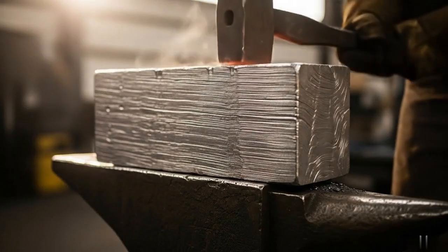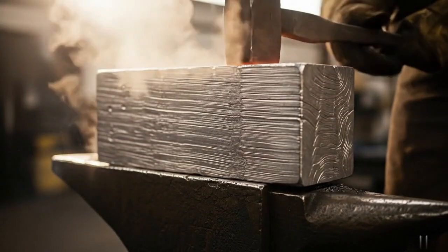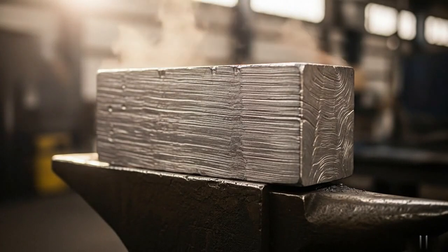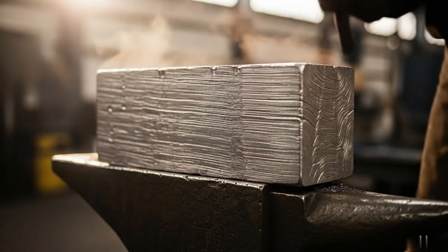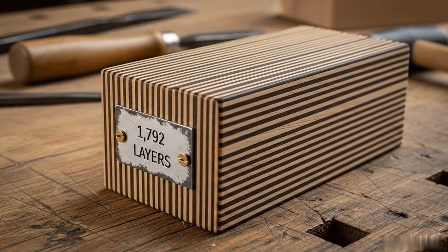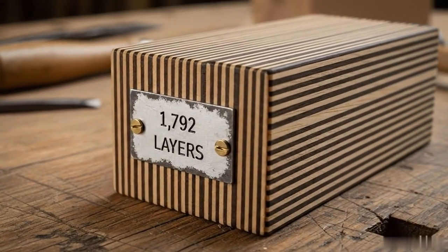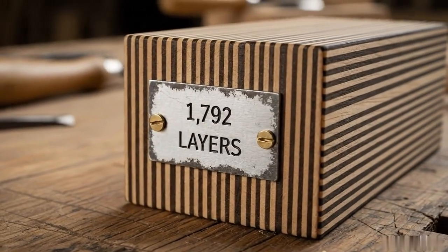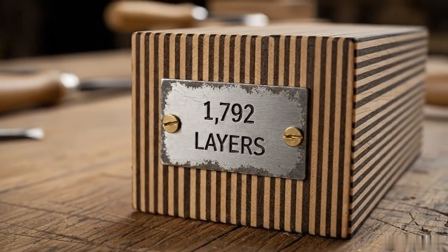After 8 folds, our little 7-layer stack has turned into a billet with 1,792 layers. This dense, layered block is the canvas for our pattern, holding nearly 2,000 layers of history.